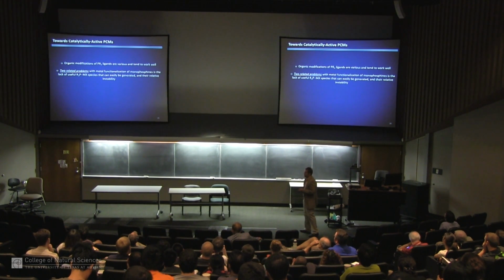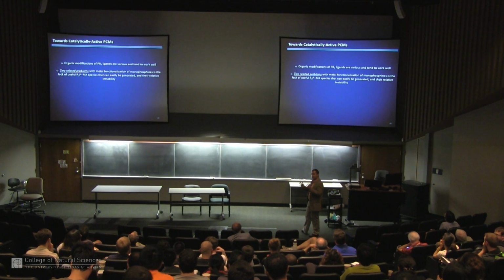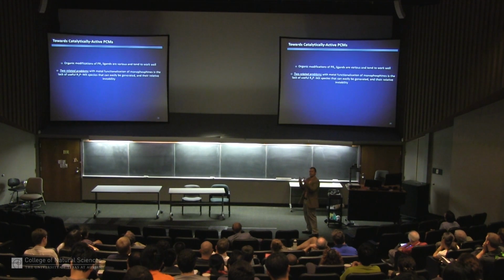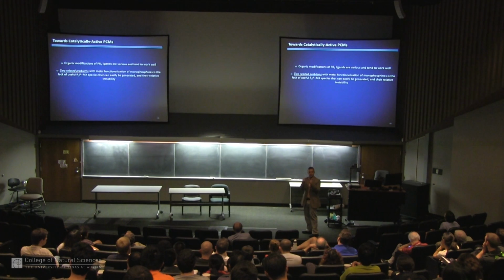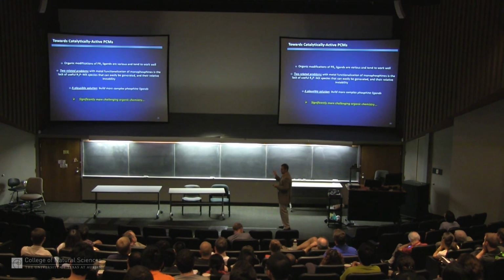So what we're doing here is addressing a problem that we found from our research, and that is that with these previous materials I showed you, yes, they're crystalline, very stable, but when we make the materials, each phosphine site, our important reactive site, is spaced at a certain distance from the next, and we can't very easily engineer the distance between the phosphines. That's what we need to do if we want to put a metal onto more than one phosphine at once. And so the phosphines are here, the metal can't use both of them at once, and we don't know how to get around that problem, apart from doing more complex organic chemistry to make building blocks that are already engineered that way.